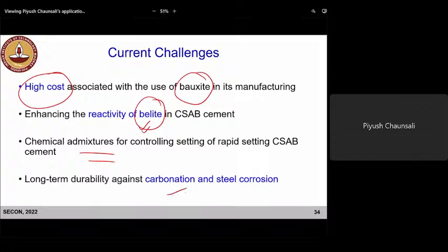And long-term durability against carbonation and steel corrosion, because the pH of these systems is lower than Portland cement systems, so there is a greater propensity to carbonate, and when it carbonates, there is also a propensity for corrosion. So there has been some work currently going on to look at that aspect.